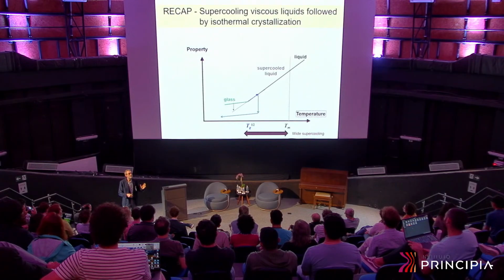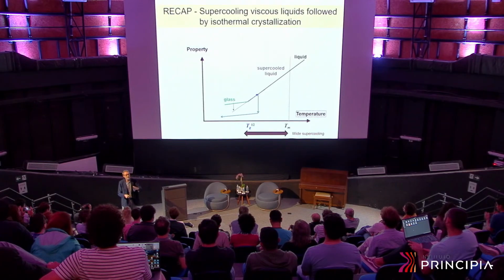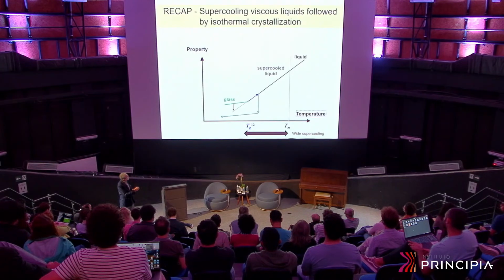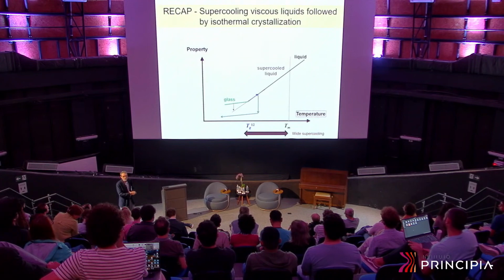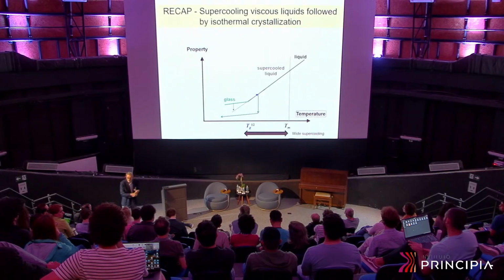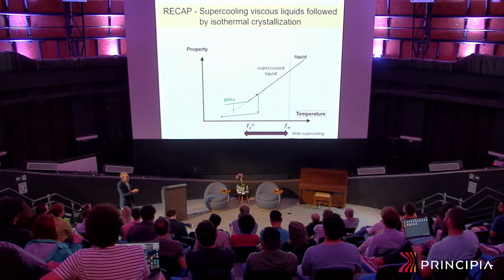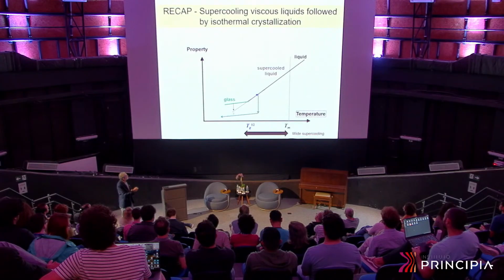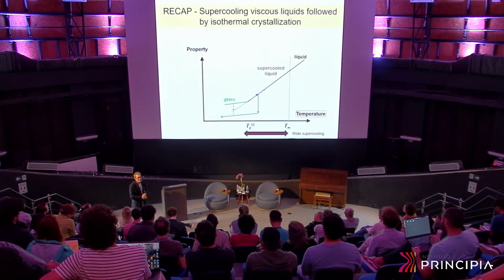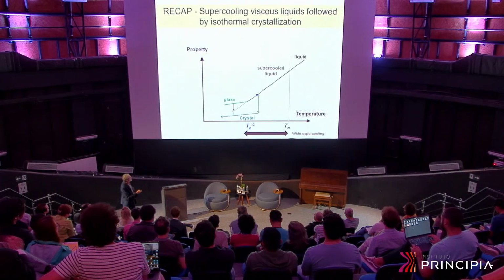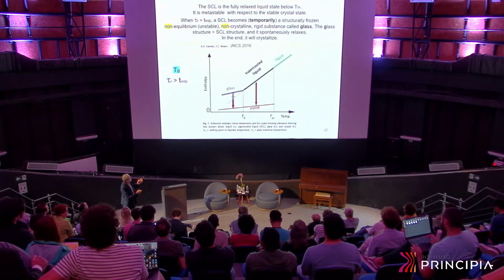All properties of glasses change with time. That's why they are not true solids. They will change with time and come back to the supercooled liquid again. Then they're soft matter again. They're liquids. If you wait a little bit longer, they will also crystallize. All glasses will eventually crystallize. It's just a question of time and how far you are below the glass transition temperature, and they become a crystal. Okay.